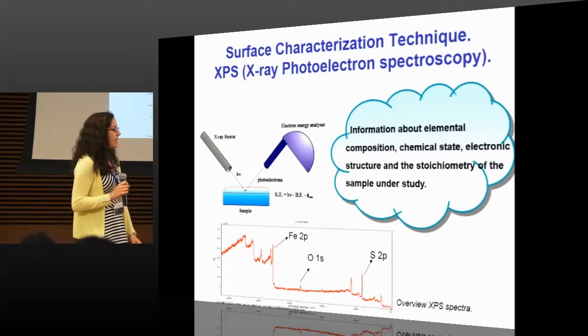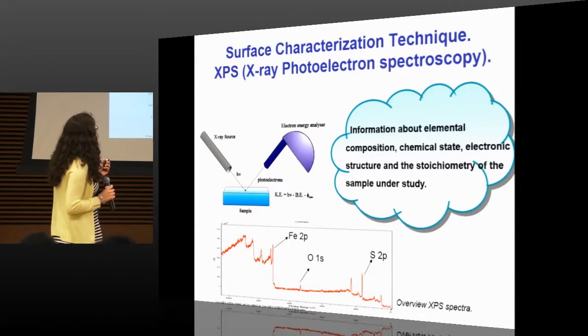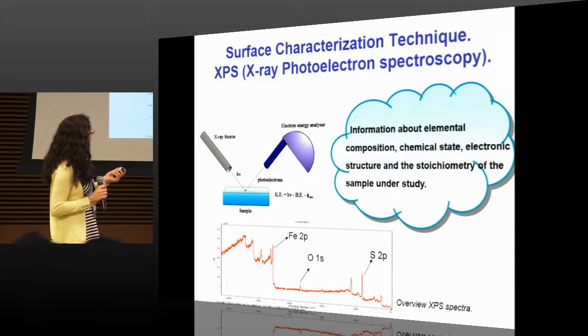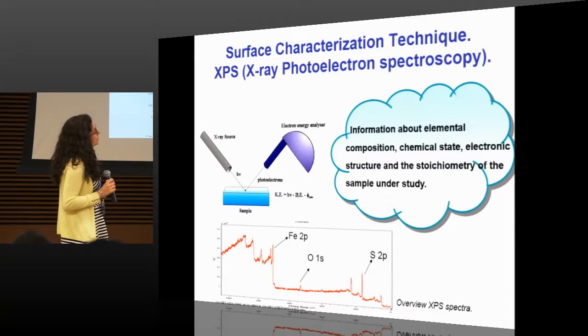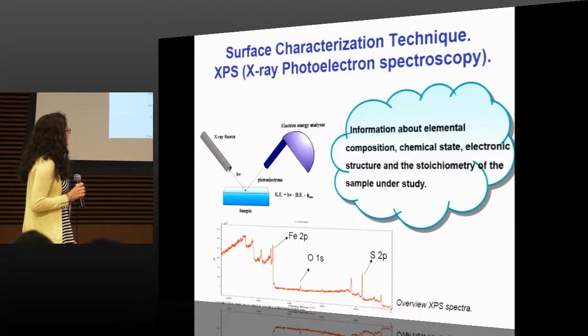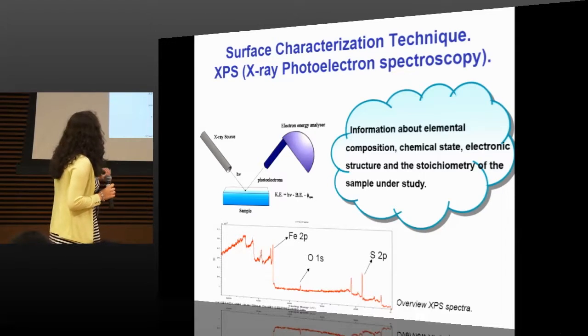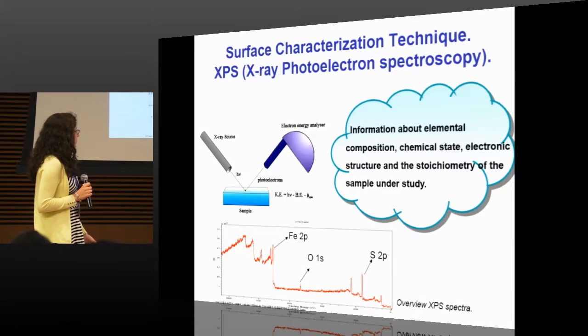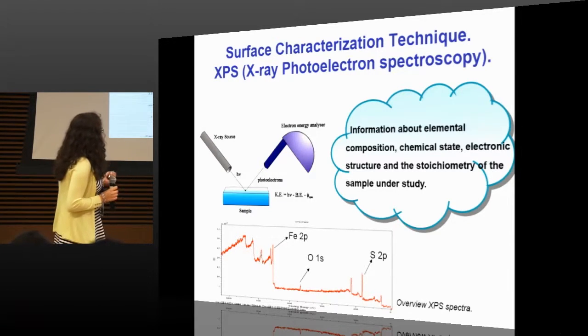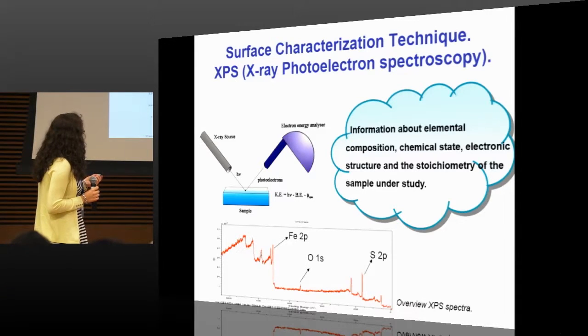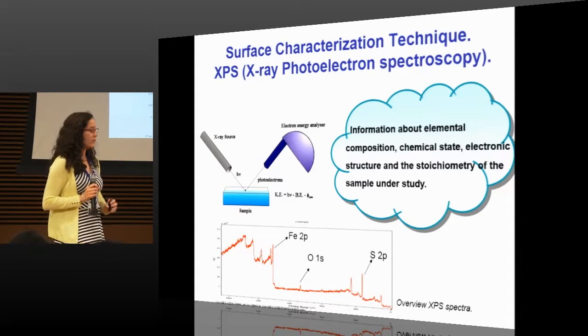In this experiment, I have been using XPS. XPS is X-ray photoelectron spectroscopy, and it's a surface characterization technique. With this technique, I can get information about elemental composition, chemical state, electronic structure, and the stoichiometry of the sample under study. Here, you can see the overview XPS spectra of the pyrite mineral single crystal, and we can observe the different regions of the pyrite: the iron region, the oxygen region, and the sulfur region. There are Auger peaks too, but in my experiment I study only the XPS peaks.